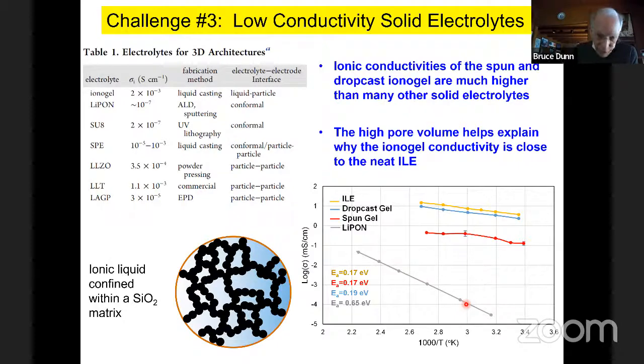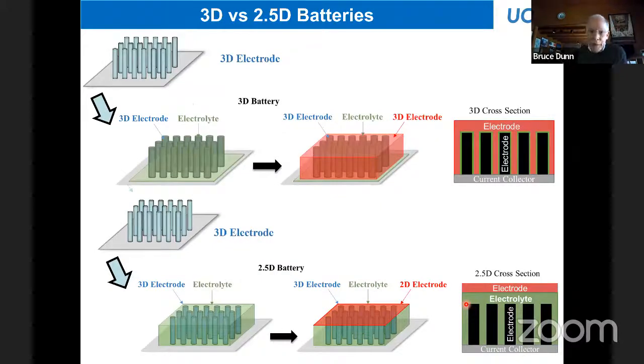The second part of this is to change the design, again with an eye towards assembly, and that is to simplify the assembly. This is where we go to 2.5D batteries. With 2.5D batteries, the counter electrode is now going to be a plate. So we're going to make arrays the same way, only now we're going to fill the region in between the posts with our electrolyte. And as long as it's conductive, you have no problem with it. And then we put on the top electrode, which is a 2D electrode. And that's what we mean by a 2.5D array.